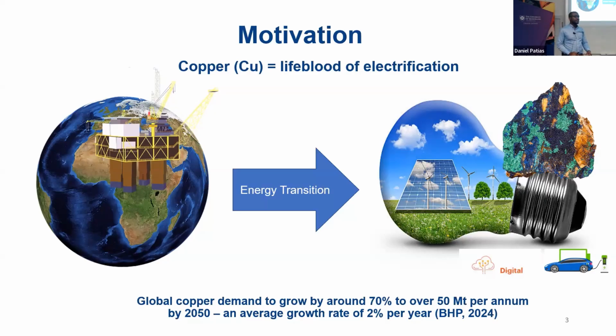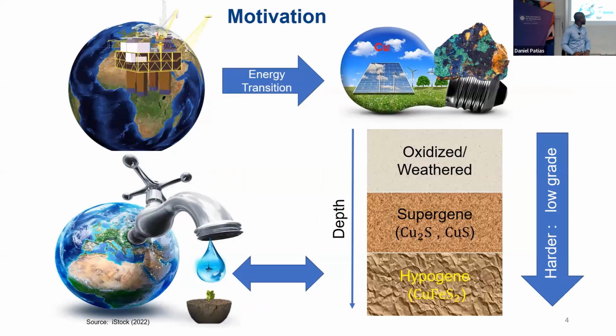But then there's a challenge where there's not much copper. So we need to produce more copper to meet the growing energy demand. So BHP this year predicted that the global copper demand would grow by 70%, to over 50 million tons per annum. So from now till 2050, we need 20 million tons more, so 2% every year increment in that direction. So to reiterate, we're transitioning from a high carbon economy to a low carbon economy. We need much more copper.